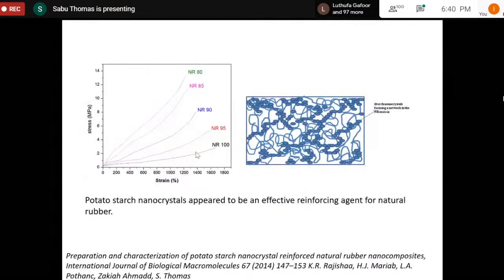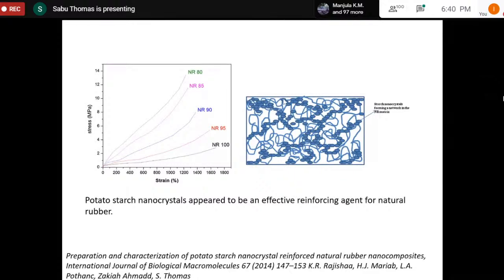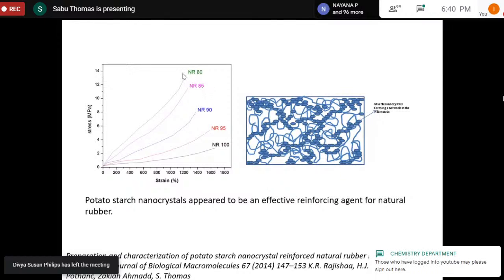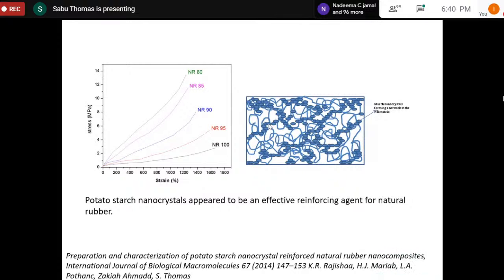The beauty of this, I can show you one slide, the effect of nanostarch. This is neat natural rubber, mechanical property, neat natural rubber. And if you put nanostarch, nanoscale starch particles, look at the mechanical properties, remarkably improved. See, the strength of natural rubber, which was not possible in this 2 megapascal, became around 14 megapascal. And you can see the network made by nanocrystals in natural rubber. So we were able to make strong natural rubber by putting starch nanocrystals.